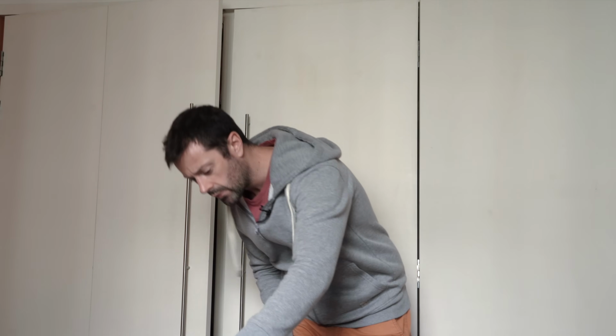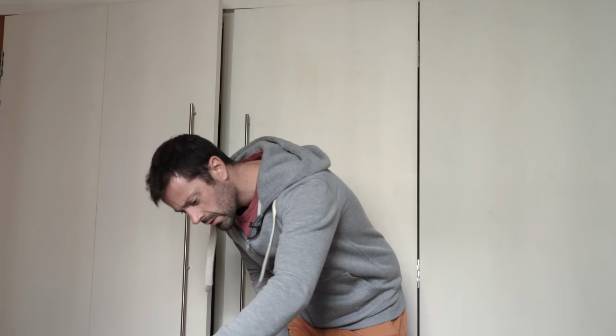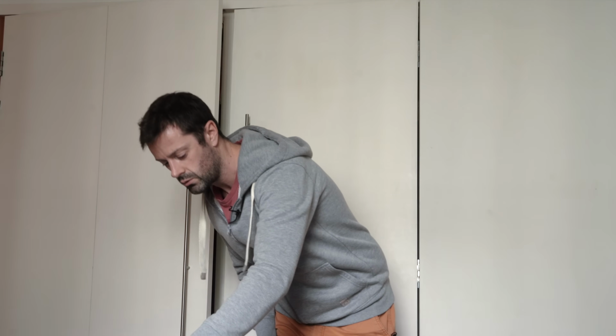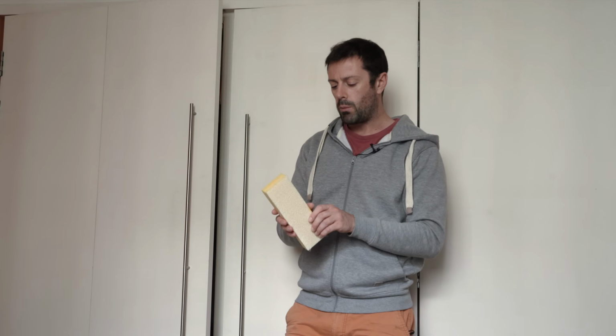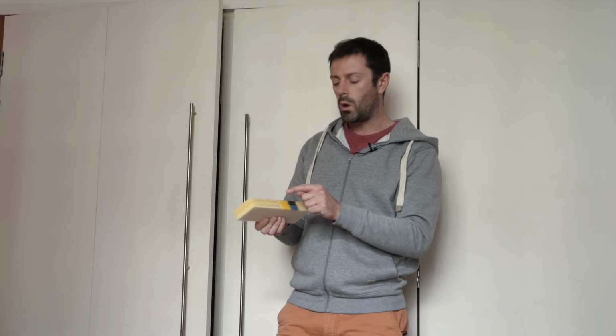As we have concluded, we're going for Gurit CoreCell, and I've gone for 2 different densities. Let me find the right ones. There's an 80 and there's 100. If you just go to composites websites, it's very common for densities around 75, 80 kilograms per cubic meter to be sold, and it's a fairly good halfway house for most applications. And we're going for one around 80 and also one around 100.